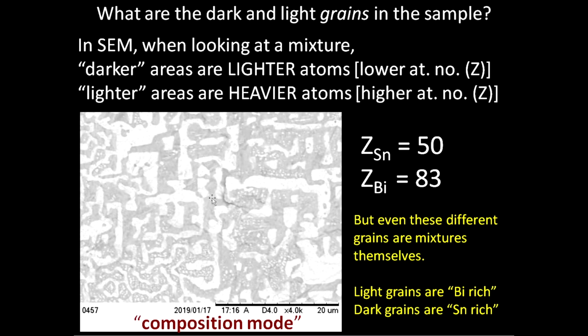But even that's not the end of the story. Even these light and dark regions are themselves mixtures. So the dark regions are not essentially 100% tin, and the light regions are not 100% bismuth. But as it says down here at the bottom, the light regions are what we would call bismuth rich. They're a very high percentage of bismuth and a low percentage of tin. And the dark regions are a low percentage of bismuth and a high percentage of tin.